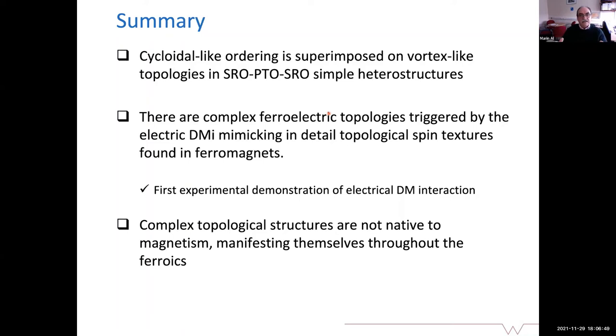So to summarize this work, we have observed a cycloidal-like ordering, which is overlapped on the vortex core, and that is a complex topology, which is chiral. It is generated, most probably, by an electric Dzyaloshinskii Moriya interaction, which maps the polarization exactly as the classical magnetic Dzyaloshinskii Moriya interaction maps the magnetization in a ferromagnet. So, in our opinion, this is the first experimental demonstration of this electrical Dzyaloshinskii Moriya interaction.